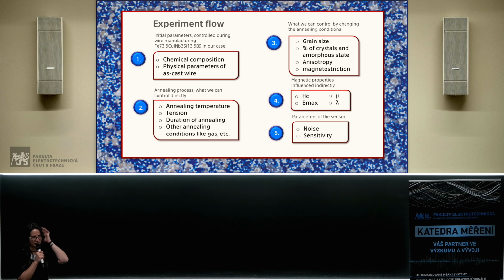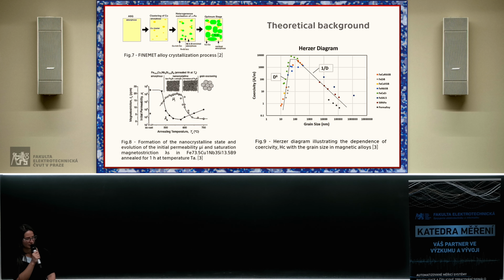And also, by changing the parameters of annealing, we can change grain size and domain size, which is really important for getting the optimum state of the material to get nice results, as well as the ratio between amorphous and crystalline state and other properties. So here are some pictures of the theoretical background.